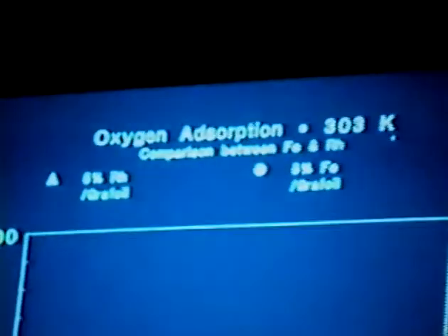Now this is a plot of differential heat of adsorption versus coverage for the two monometallic catalysts. Now I didn't mention at this point, the catalysts were typically loaded at about 5 weight percent. We're looking at 5 weight percent rhodium on graphite foil and 5 weight percent iron on graphite foil. The iron data, you can see that they're very different heat signatures, is what I'll call it. Iron is fairly steady for a long period of time, up to about 3/4 total coverage. It then drops off rather dramatically until you reach the physical adsorption region, and then we're measuring physical adsorption heats down here. The integral heat of this, if you integrate the area under here, you can get an idea of the integral heat, and it's about 130 kcal per mole, which is what you would expect for oxidation by forming iron oxide essentially on the surface of these large iron particles.